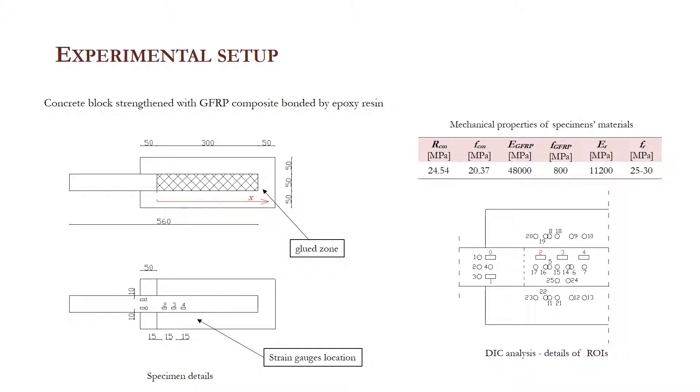Successively, several tests were performed on prismatic concrete blocks reinforced with pultruded E-glass FRP. A two-component epoxy resin was used for bonding. The tests were performed under displacement control until failure occurrence.